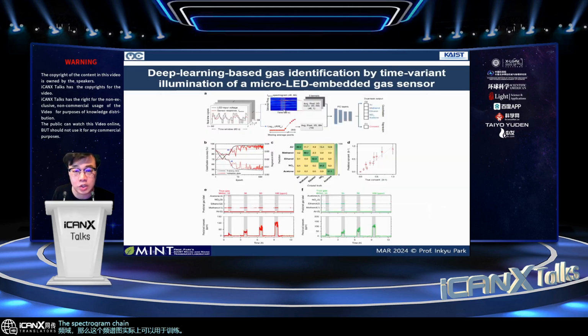This spectrogram change is used for the CNN training of the gas sensor response. This is able to give us real-time classification of gas type and concentrations. You can see the confusion matrix, compared to the previous result, the classification accuracy is relatively lower, and the mean absolute error is a bit higher. The point is that instead of using multiple gas sensors, we use only a single gas sensor. But by using this dynamic signal, we can make a classification and also regression quite accurately.